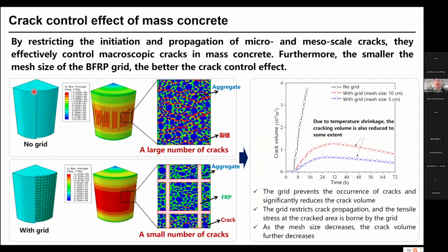Okay, so by using this method, especially for mass concrete like this kind of bridge tower, where the diameter is very large and the thickness is typically over 1 meter, sometimes over 2 meters. In this mass concrete, under the curing stage, cracking is typically difficult to avoid. By using the grid in a very thin layer, because it is free of corrosion, a very thin cover is possible, and it can control the cracking well. These are the simulation results. You can see that without the grid, the cracking goes very fast. By using the grid, the cracking can be well controlled.